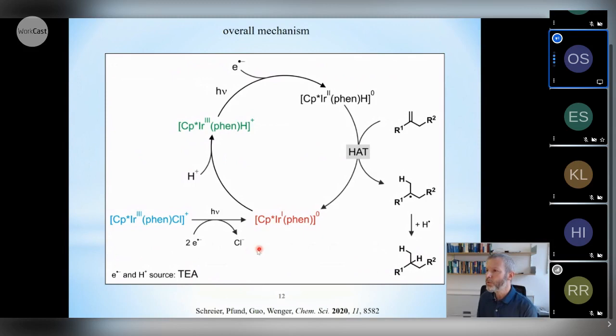Nevertheless, we arrived at this overall proposed mechanism where the iridium chloro precursor compound, which is nice to handle because it's benchtop stable, you can activate through reductive dehalogenation in presence of visible light and sacrificial electron donor to this isolable iridium-1 intermediate lacking a ligand. This can be protonated, I've shown you that, and you will get the iridium-3 hydride.